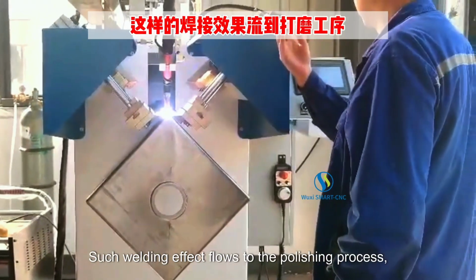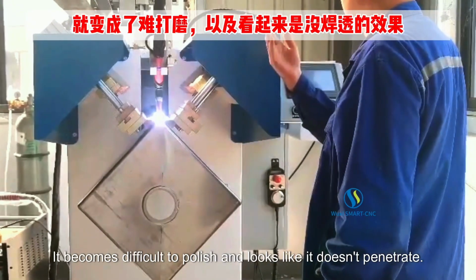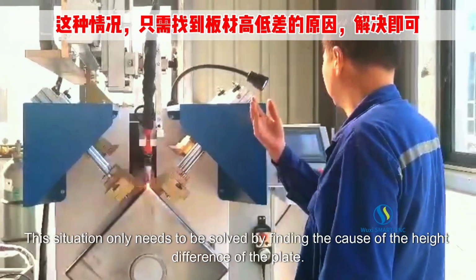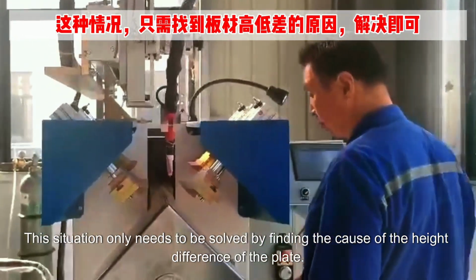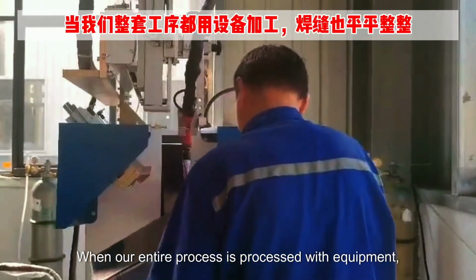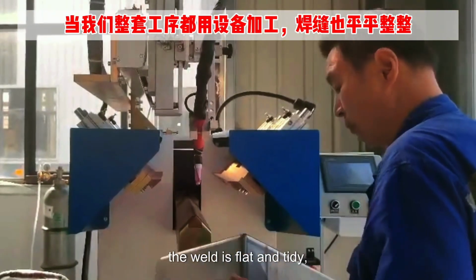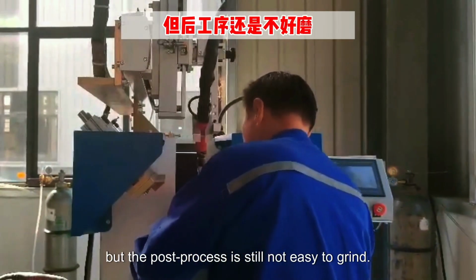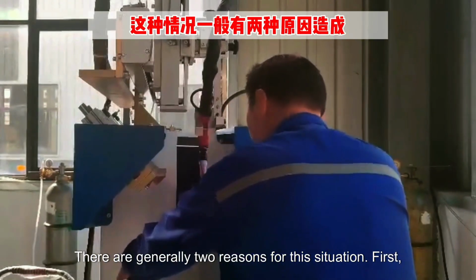Such welding effect flows to the polishing process. It becomes difficult to polish and looks like it doesn't penetrate. This situation only needs to be solved by finding the cause of the height difference of the plate. When our entire process is processed with equipment, the weld is flat and tidy, but the post-process is still not easy to grind. There are generally 2 reasons for this situation.